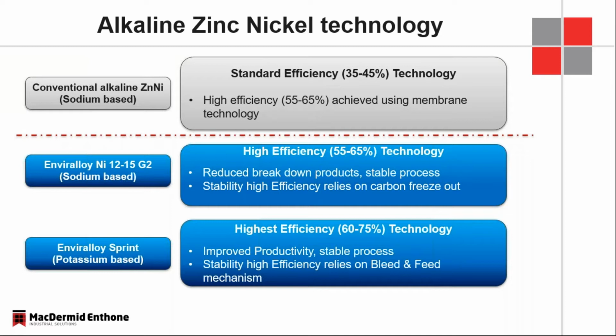And breakdown products, as anybody who has run zinc nickel knows, are extremely important. You basically don't want to destroy the heartbeat of the system, being the systems that have these products in an inverse relationship to good versus bad. For instance, if you have a complexing agent that all alkaline systems have, that's the good product. The breakdown products from those complexing systems really inhibit the efficiency, slow down the system, increase specific gravity, and need to be removed. Also with the sodium carbonate, it has to be frozen out. We've all who have used zinc nickel have had to deal with freezing out sodium carbonate, whether on a routine basis or on a batch basis.